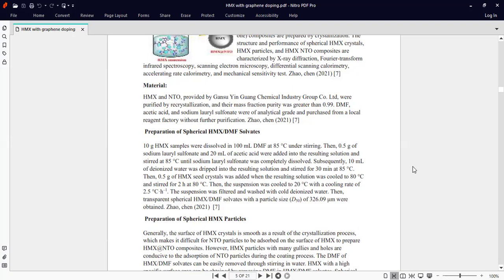Then the suspension was cooled to 20 degrees Celsius with a cooling rate of 2.5 degrees Celsius per hour. The suspension was filtered and washed with cold deionized water. The transparent spherical high melting explosive DMF solvates with a particle size of 326.09 micrometers were obtained.